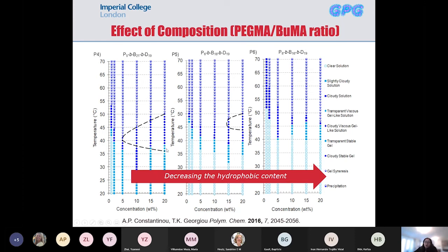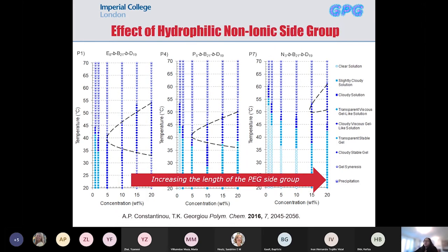And also very close to what we were aiming at, 37, but ideally, if you do want a gel at 37, you want the gelation to happen a bit lower, so the gel at 37 is a stable gel. So we still wanted to have it a bit lower. So in this case, we increased the length of the PEG side group, and that means we made the polymer more hydrophilic. And similarly as before, the gelation area shifts to higher concentrations and higher temperatures. So the more hydrophilic, the higher the gelation temperature.